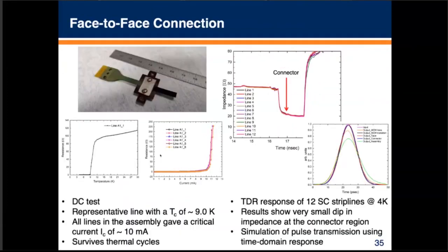Okay, so then on to the most recent one, face-to-face connections. I don't show a whole lot of details here. There's some abstracts outstanding, but I'm showing a little bit of hints here to hopefully get some interest. So in this case, instead of the cables being abutted to each other, they're just face-to-face. The signals are facing each other. And if we look at the DC properties of these, you can see it's showing a TC of 9, it's niobium, so there must be a small little offset in terms of the temperature there.